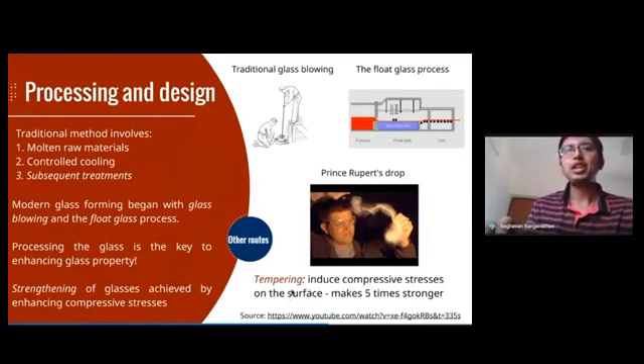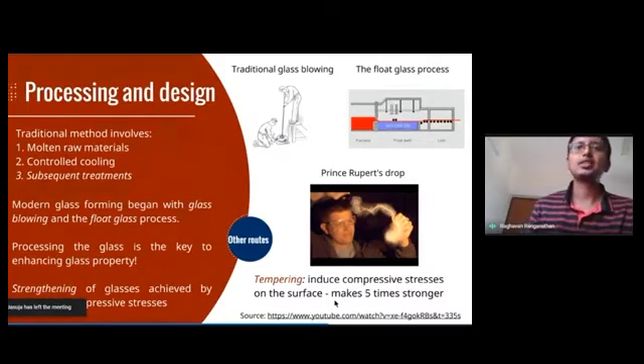In fact, it's called tempering, that makes compressive stresses the go-to method for increasing the strength of glass. And quite routinely, we can make glasses that are about 5 times stronger than traditional annealed glasses.